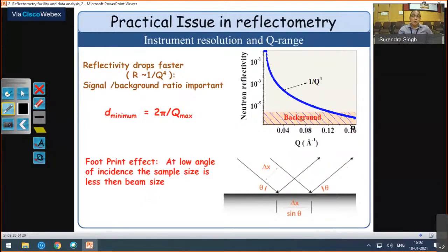Because the Q maximum for this reflectivity pattern will decide what should be our minimum thickness, 6 angstrom, 7 angstrom, on a substrate we can detect from an instrument. And that gives this relation: d minimum becomes 2 pi by Q maximum.